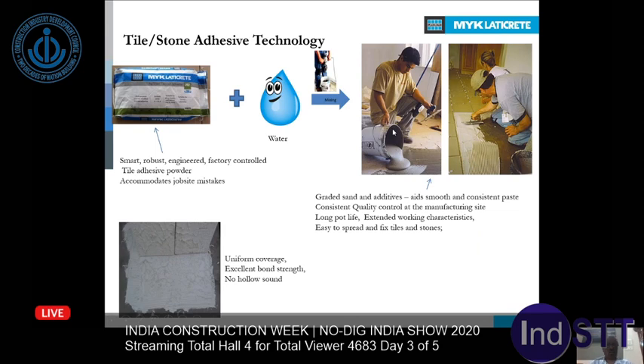So what is the alternate? That's what we call modern adhesive technology. This is basically a factory made engineered cement, and it comes with a lot of additives, based on the nature of the application, and controlled cement and controlled sand gradation with good quality additives. It comes in an airtight bag, so that means you can carry it anywhere, keep it for a longer time. And at the time of application, you take it and add just water, nothing else. Then mix it thoroughly in a bucket with a stirrer mixer. Then that's what you get.